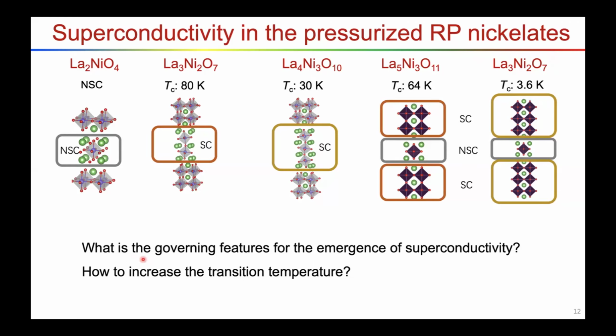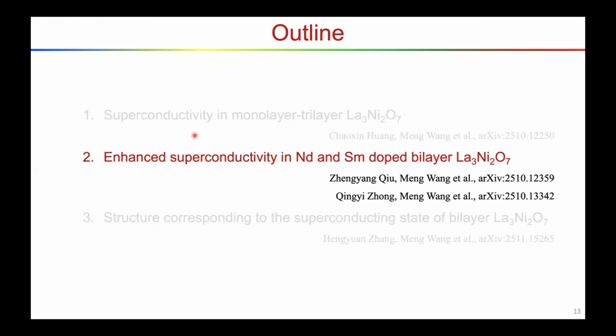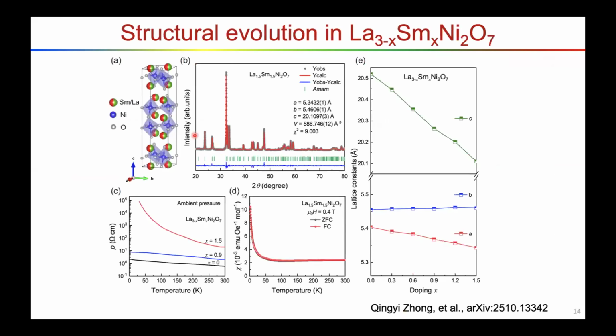So we want to know what the governing features are for the emergence of superconductivity and how to increase the transition temperature. It seems the bilayer phase is very suitable for searching for high temperature superconductivity. So we doped neodymium and samarium into this compound. When we doped samarium, we can decrease the C lattice constant.